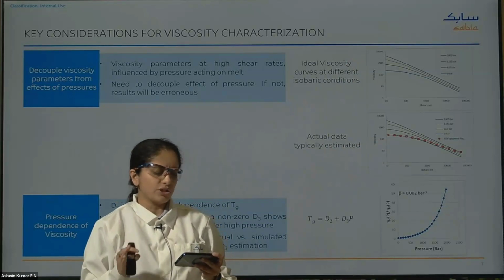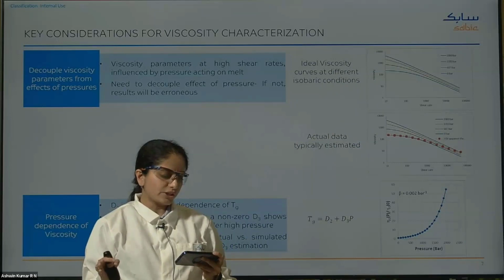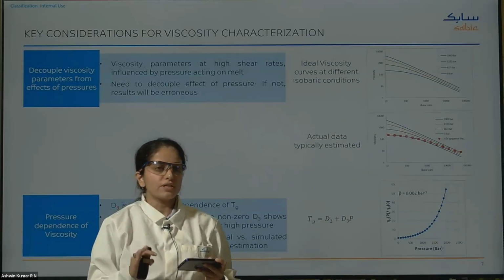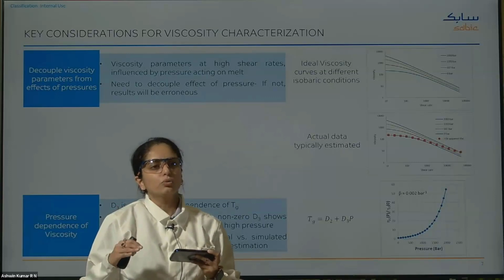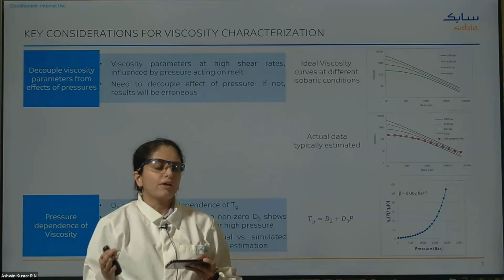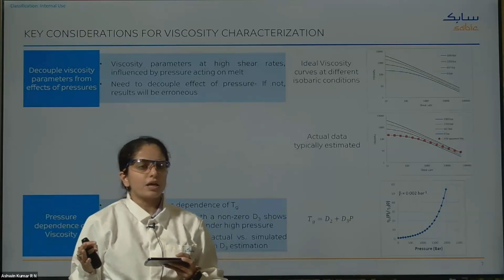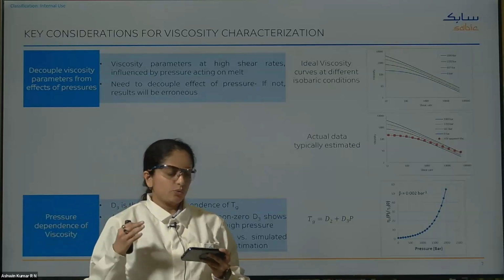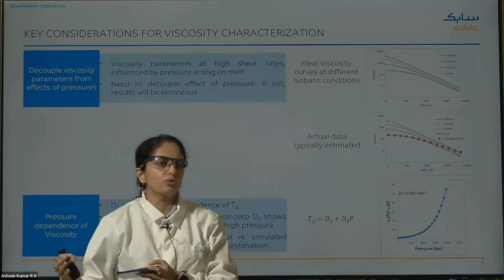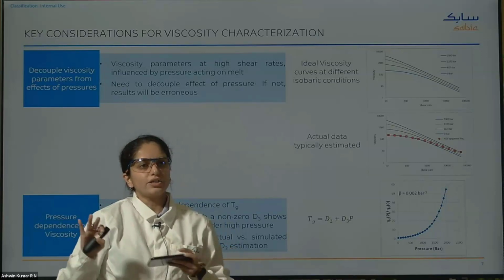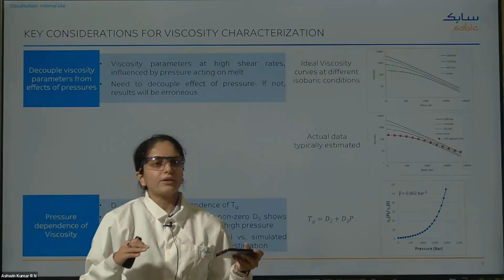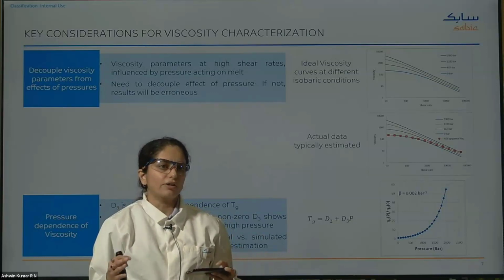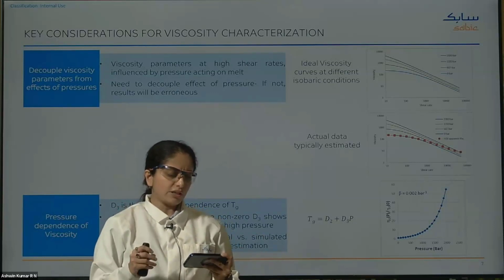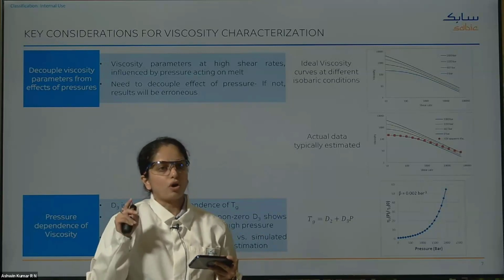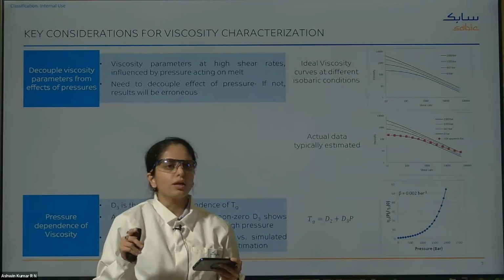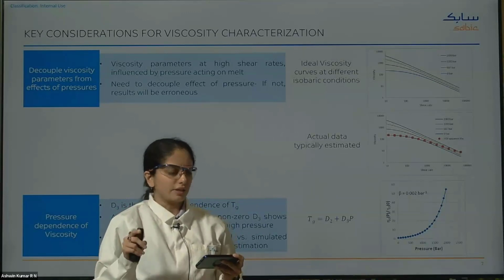Dynamic rheology is used to measure the viscosity at 0 pressure, and the polymer must fulfill 2 conditions. The first condition is that it should be able to follow the time-temperature superposition principle, wherein you can generate complex viscosity master curves. The second condition is that the polymer needs to follow the Cox-Merz rule, which is a simple relationship wherein we correlate the steady shear viscosity with the complex viscosity, which is a function of the angular frequency. By achieving these 2 conditions, the Cox-Merz rule and the TTS, we can have this D3 characterization.